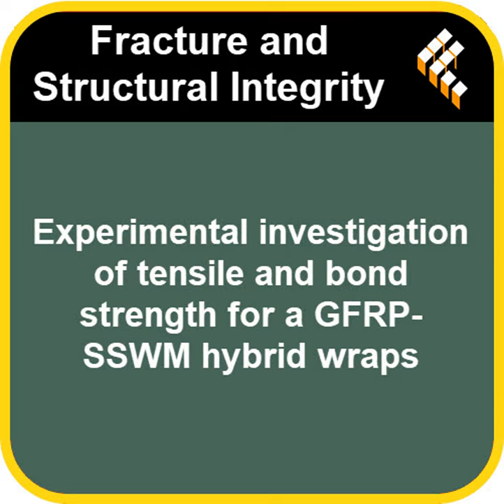Only 40%? Why so low? Because failure wasn't usually the GFRP breaking. It was either the concrete underneath crushing or, more often, the GFRP debonding from the concrete surface. It peeled off before the fibers could take their full load. So a lot of wasted potential strength. A significant amount. Now, compare that to the pure SSWM wraps. Their utilization was much higher, over 83% with Sikadur 330 and nearly 90% with Sikadur-30 LP. So the steel mesh sticks much better. It seems to create a much more effective bond, allowing it to use more of its inherent capacity.